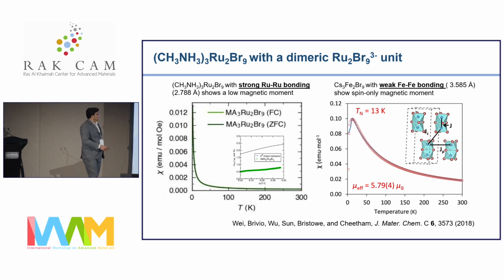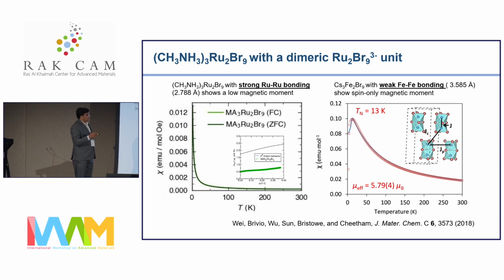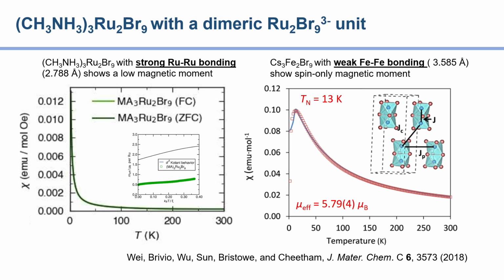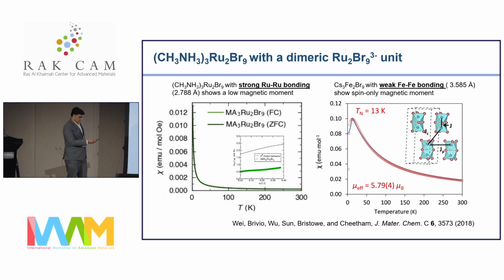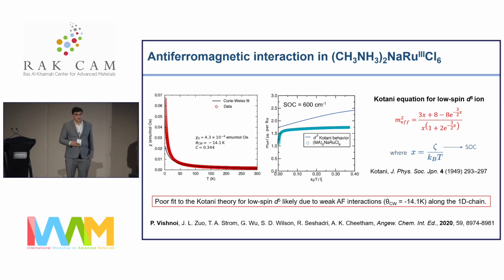Whereas the earlier report on iron, which has about 3.6 angstrom distance between the 2 iron centers, doesn't show any quenching of magnetic moment. The magnetic moment obtained from the experiment is close to the theoretical moment based on the spin-only formula. That means the 2 iron centers in the dimer are not interacting antiferromagnetically. Well, then we also looked at the magnetic data of the 1D structure, one of these 6 1D structures. What we see is the system interacts antiferromagnetically.